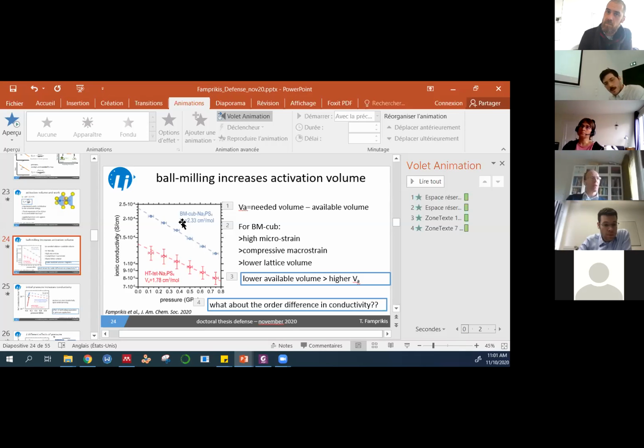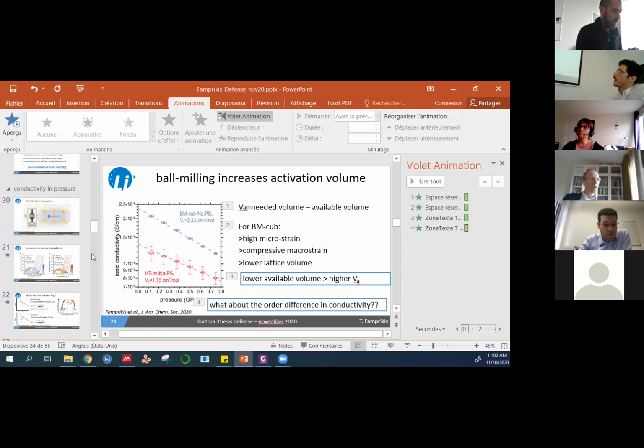One thing I was also wondering if it's possible to explain is when you fit your ball-milled cubic sodium 3PS4, then you fit it with sodium on the 24F position, right? Which is like an in-between position, let's say, between what you would think is the equilibrium position and the saddle position towards the next site, right? Yes, I tried multiple different positions to explain what is apparent as a sodium disorder, but the one that fits best is indeed 24F.